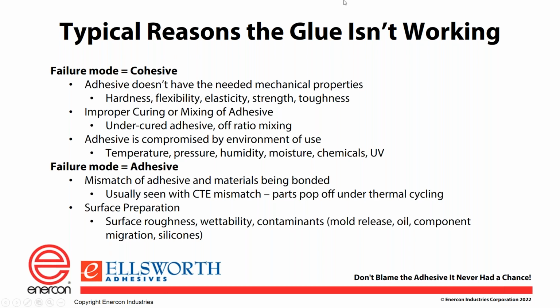So again, if your failure mode is cohesive, that means that your adhesive doesn't have the needed mechanical properties for your assembly to do what it needs to do. So you may need to modify the hardness, the flexibility, elasticity, strength, toughness, and probably more things as far as how the adhesive performs. You may have had an issue with applying the material. So you may have not mixed the adhesive properly if it's a two-part system, or you may not have applied enough energy or time to allow it to harden completely to its full properties.